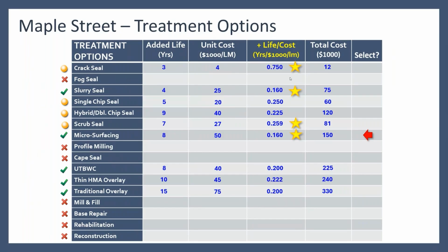So we take this forward to our supervisors, and they say, microsurfacing is something that we would like to add. Notice in that picture we had curb and gutter. So one of the things that you want to avoid, if you did a traditional overlay, you would probably actually have to mill and fill, or you're going to pave into the curbs. You're going to mess up some of the drainage. Something very thin as a surface treatment is going to allow drainage patterns to stay essentially the same. Curbs still function. Microsurfacing is very thin, so that is also an advantage, and it looks like it's been repaved. So aesthetically, practically, maybe not the best monetarily, but this was the one that was chosen.